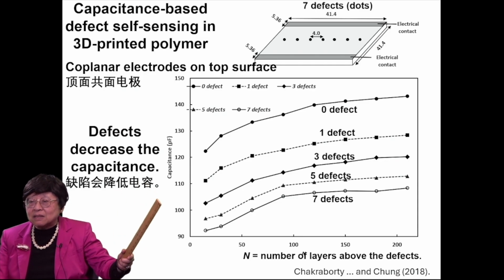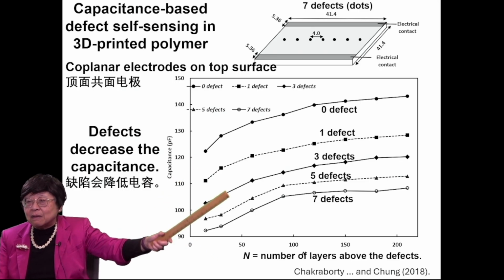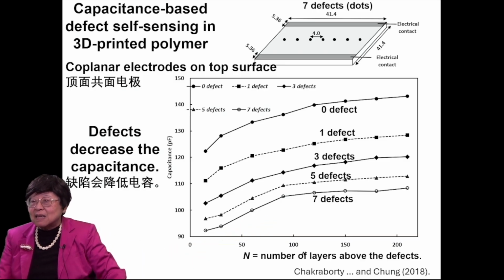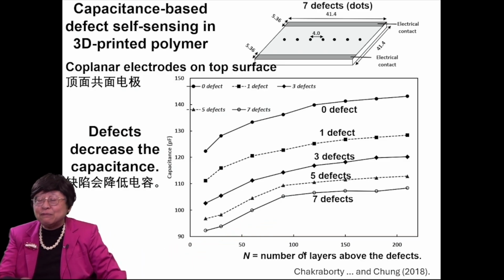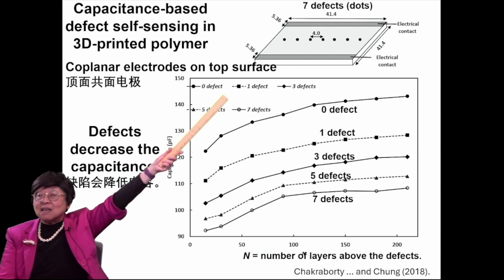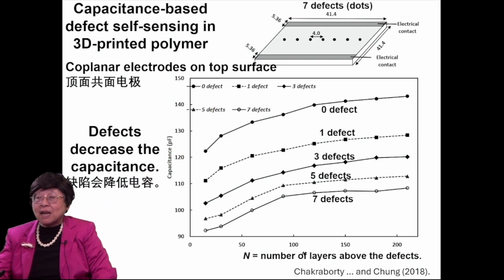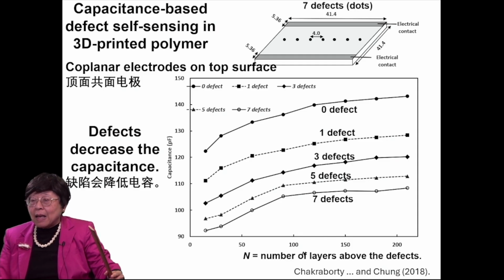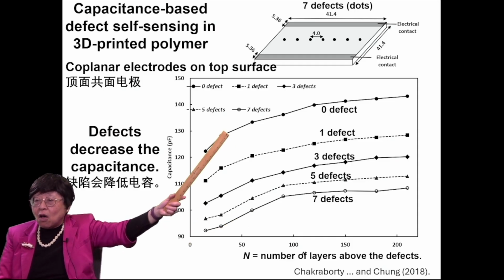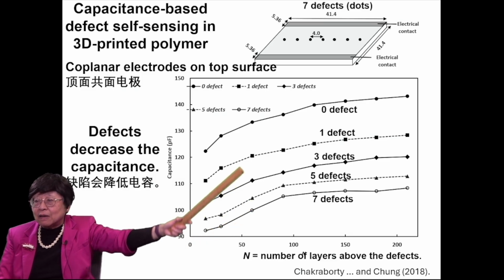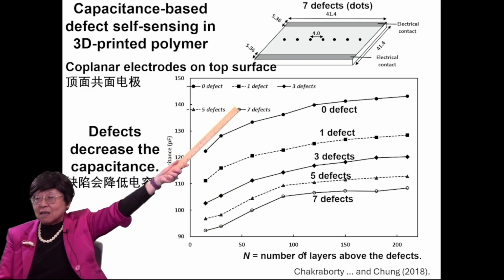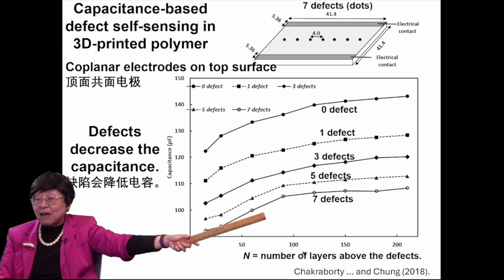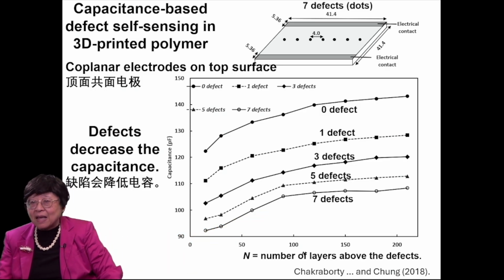And this shows the capacitance versus the number of layers above the defects. The more the number of layers above the defects, the bigger the capacitance, because the defect is deeper down, and you are measuring the capacitance using coplanar electrodes that are on the top surface. Also, the larger the number of defects, you have shown the picture of 7 defects, but I can have 0, 1, 3, 5, 7, different numbers of dots there. And the larger the number of defects or dots, the lower the capacitance.